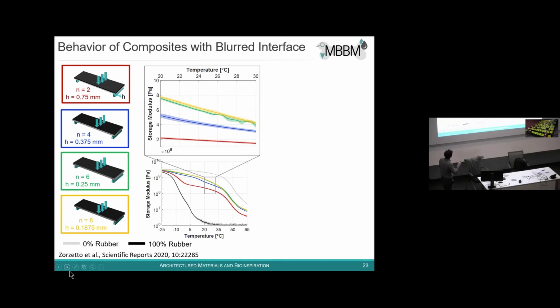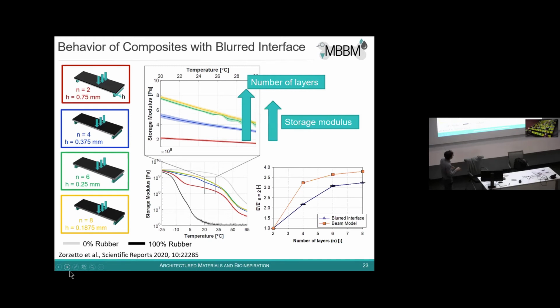And what we see if we have a so-called blurred interface, so the 150 micrometer interface, is that when we increase the layers from 2 to 8, the storage modulus increases. And this is not surprising. This is also in agreement with composite beam theory. Simply because you are redistributing the stiff material across the interface, you get a bit more rigid behavior. Okay, this is something that is predictable, understandable, and we were happy.